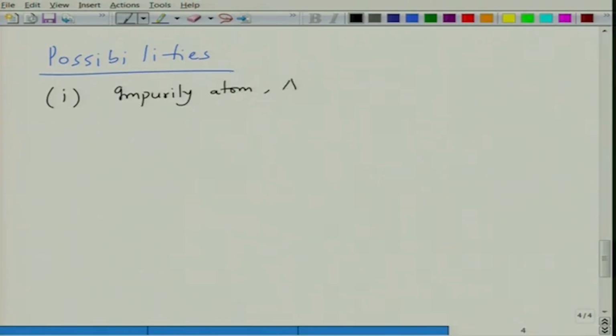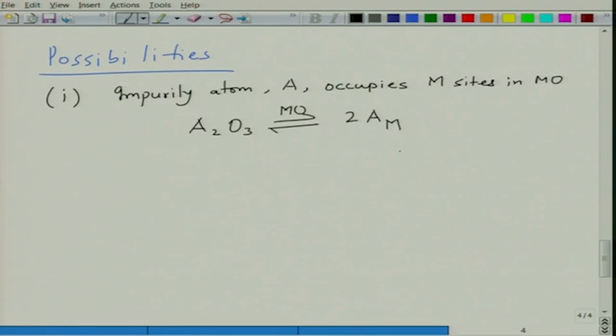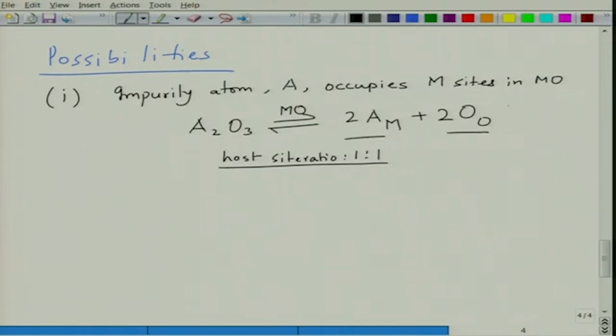impurity atom, which is A, occupies M sites in MO. Okay. Now, if that happens, let us say A2O3 goes to MO. Okay. So, which means 2A go to M site. What must happen? MO host lattice has a site ratio of 1:1, right. This is the host site ratio, and impurities cannot disturb that. So, when 2 A's go to M site, 2 oxygens go to oxygen site. So, site ratio is maintained, which means the extra oxygen has to